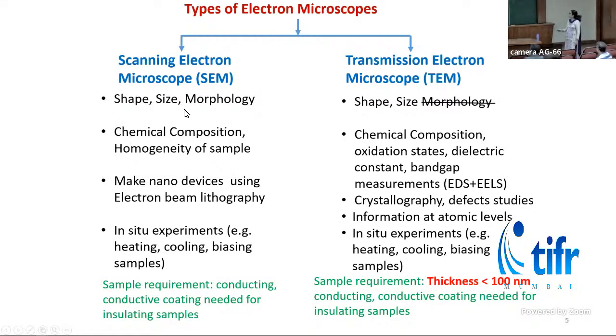We can see shape, size, and morphology of the object using SEM. If we have EDS, energy dispersive spectrometer attached to it, we can find the elements present in the sample and also detect the chemical composition of the sample. If we have electron beam lithography system attached to the SEM, we can make nano devices using SEM. If we have heating, cooling, biasing holders, we can do some in situ experiments to study real-time dynamics in the sample. SEM needs conducting samples, and if the sample is not conducting, then some conductive layer of carbon or gold is needed.